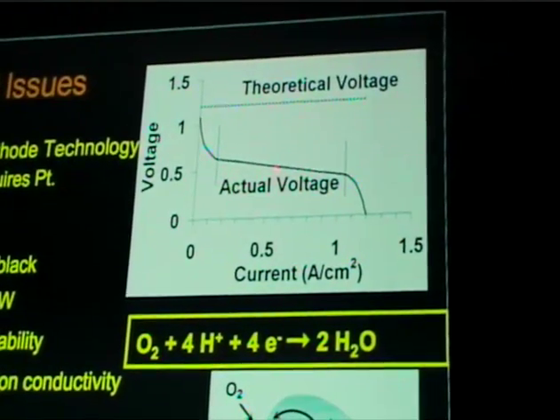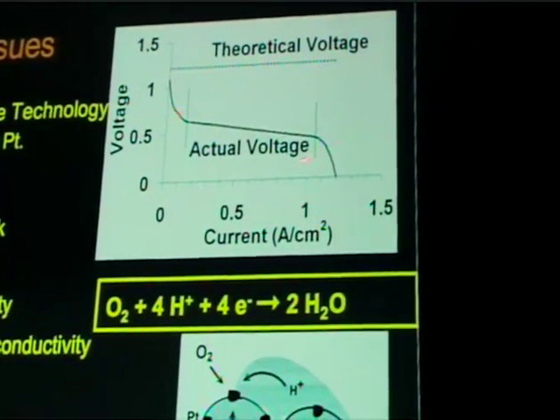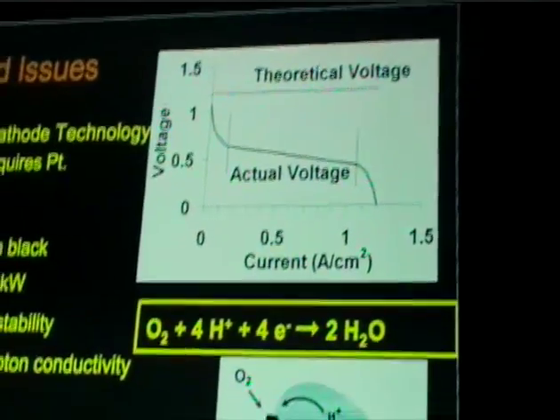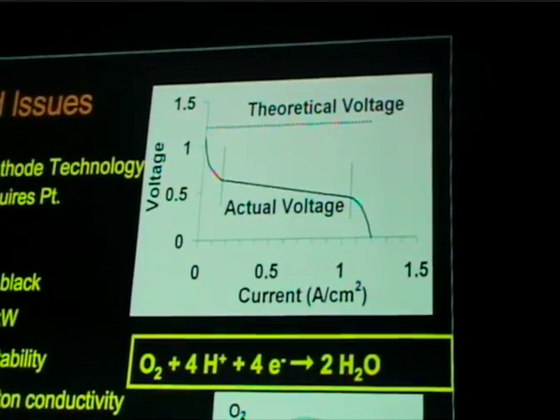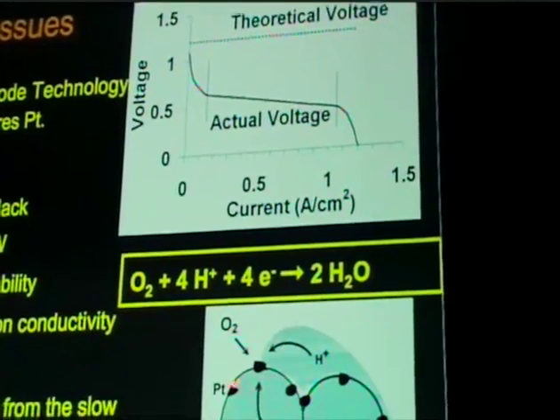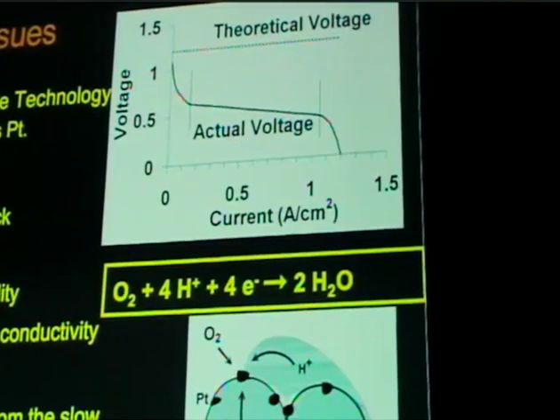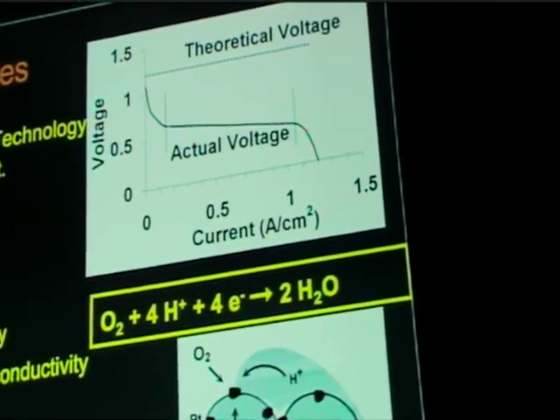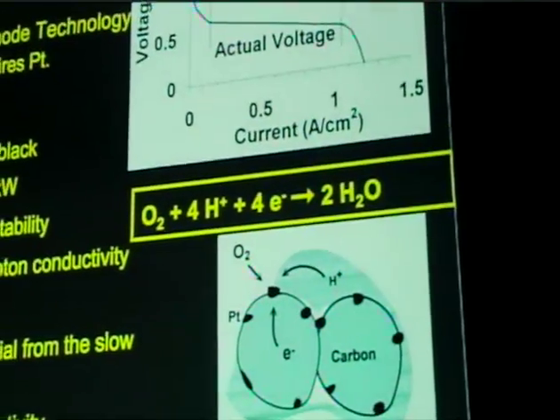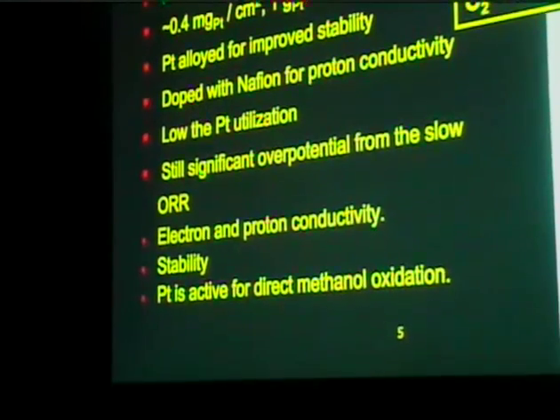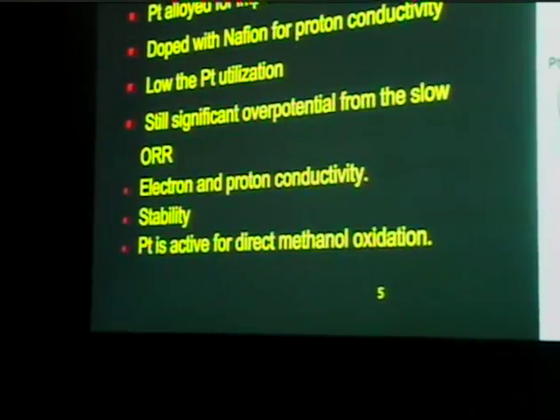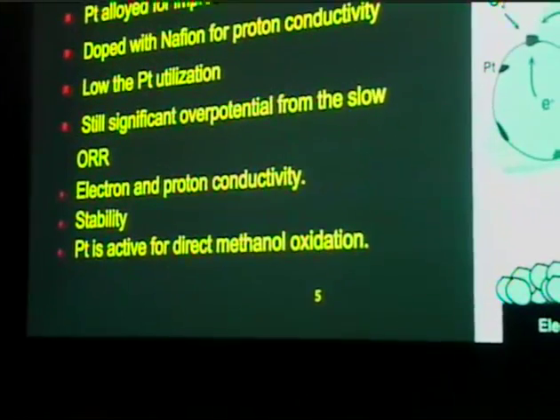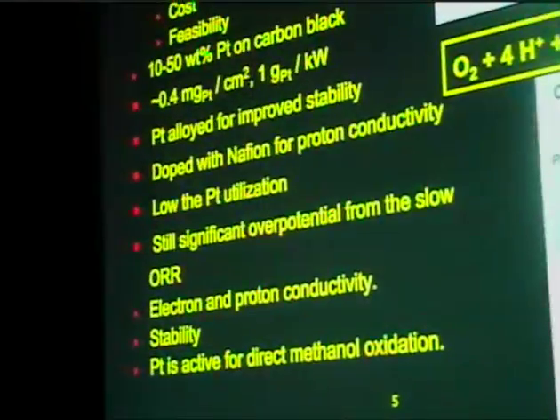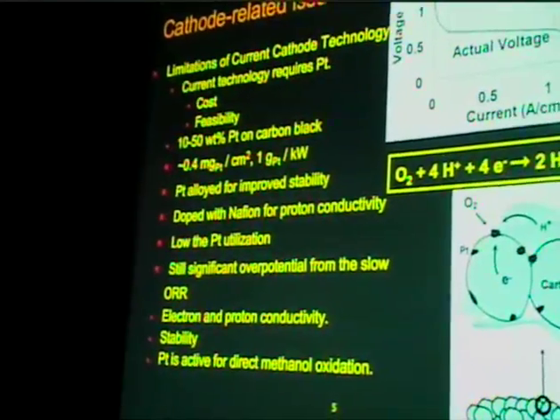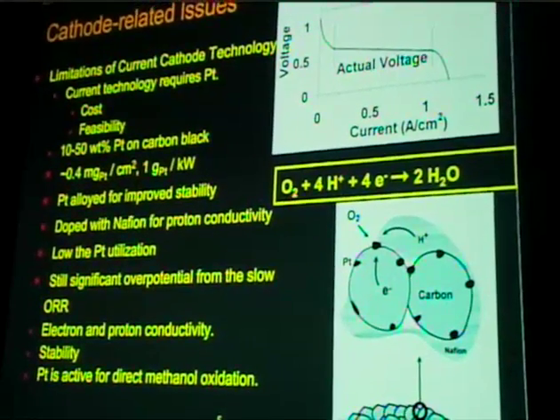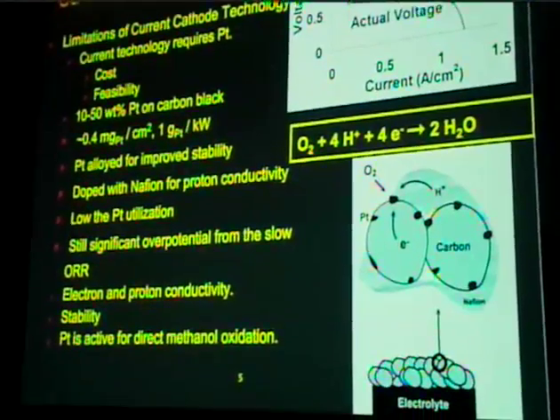In here, we have the resistance-related ohmic losses, and then if you go further in the higher currents, we start seeing potential losses because of mass transfer limitations. So the challenge is really bringing platinum, electrons, oxygen really together, and also have high both proton conductivity and electron conductivity. Another problem with platinum is the fact that it is active for direct methanol oxidation, which creates a problem with direct methanol fuel cells, because methanol can cross through the polymer membrane, and then if we are using platinum as a catalyst on the cathode side, it oxidizes and really causes further potential losses.